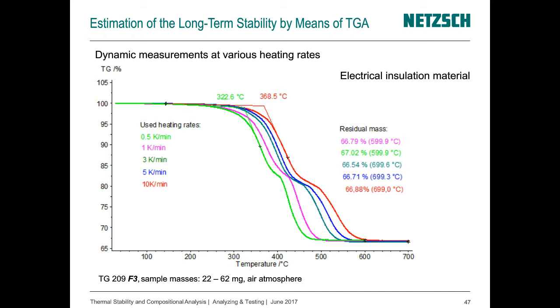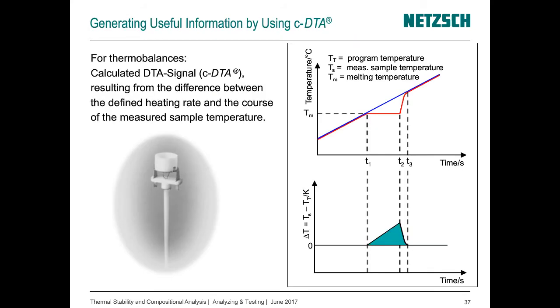I don't know if all of you can see the slide on the screen now. In the left part, there is a presentation of the sample holder, and if you look closer, you can see small wires, and these small wires represent the thermocouple, which is measuring the sample temperature. And if the sample thermocouple is in close enough contact with the crucible, then it can detect any temperature changes inside of the sample. This signal is then compared to the program temperature, and the difference between these two values is used to calculate the CDTA signal. This is represented as a scheme in the right part of the slide.